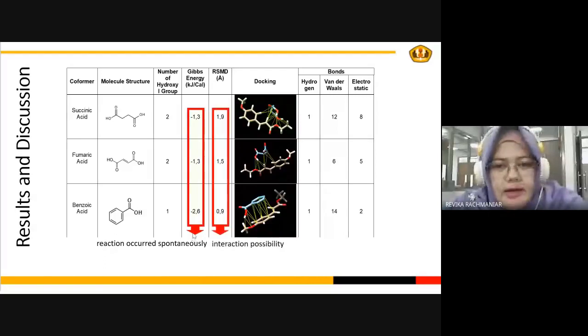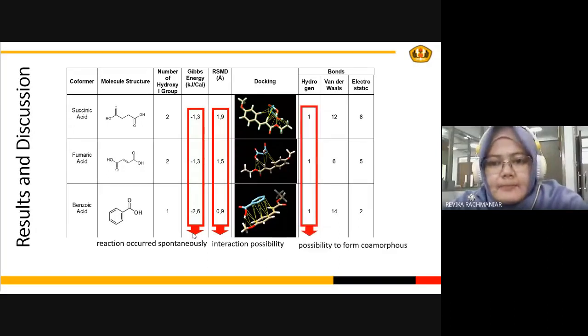Meanwhile, the RSMD value of this interaction is below 2. It means that the interaction is possible. And from the interaction, we see hydrogen bonding between these three coformers and APMC, so it has the possibility to form a coamorph, strengthened by van der Waals and electrostatic force.